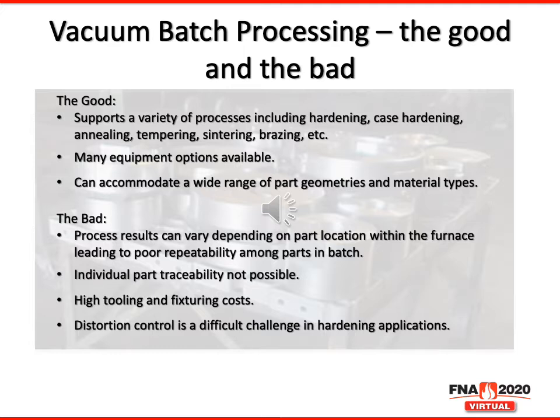However, those good features come with some specific drawbacks. First is when the parts are loaded into the furnace, naturally we're putting several into the furnace at once, which means the furnace has to be tuned to handle that entire batch. Because of that, not every part receives the same treatment, if you will. So there is part variation or result variation within the batch itself. And we'll look at the details to this in a moment. Also, we have to treat each batch as an individual. We can't treat each part as an individual.